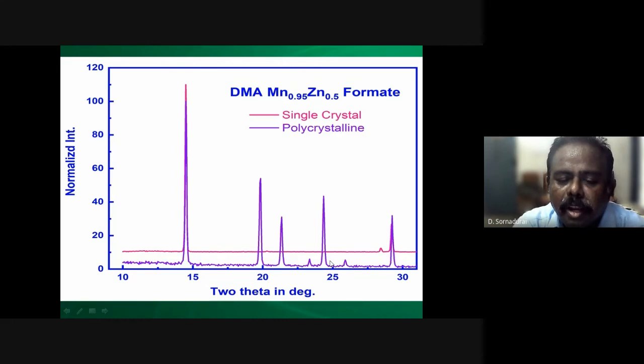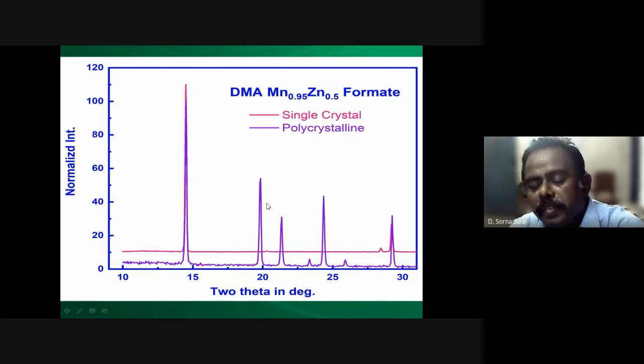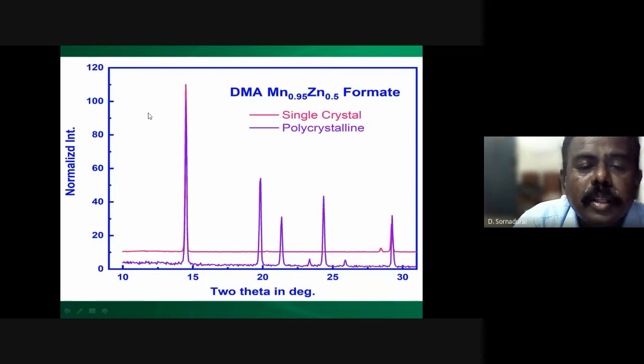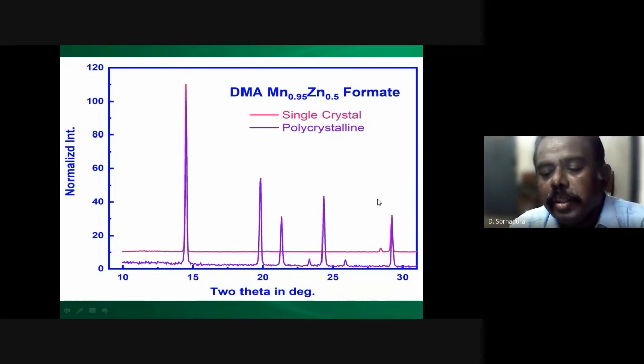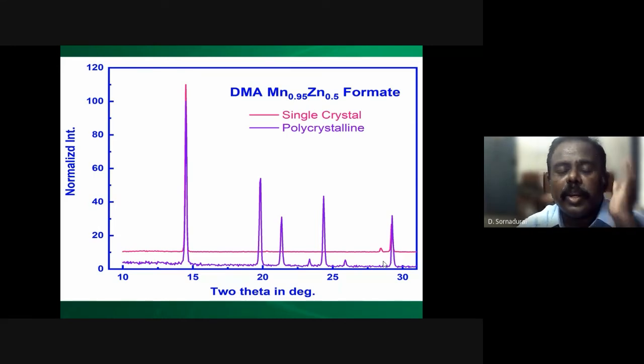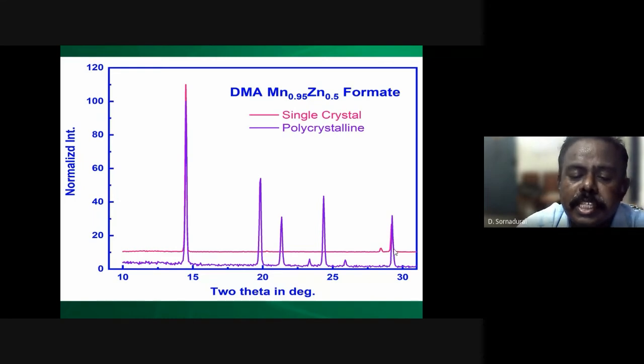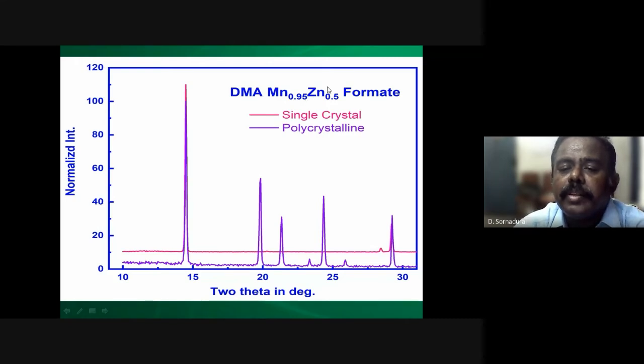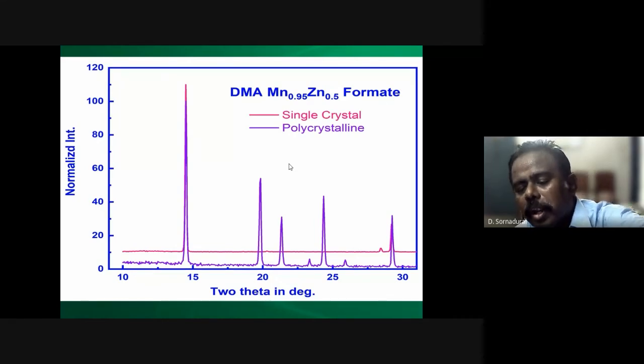But there is no single signature of any peak rising here because they are from different planes. For a single crystal, if it is 110, then 220 will be the set of planes that appears, and only in the powder crystalline. Just for testing I have taken this, and this is for dimethyl ammonium manganese 0.95, zinc 0.05 formate. So you can see the difference between the single crystal and the polycrystalline sample of the same material.